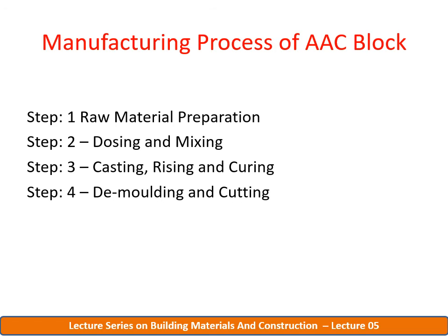This process must be continuous without significant long gap. If there is a gap between charging and discharging of the ingredient, the residual mixing might start hardening and choke up the entire unit. This process is completely automated and require minimum human power. So here, next step is casting, rising and curing.